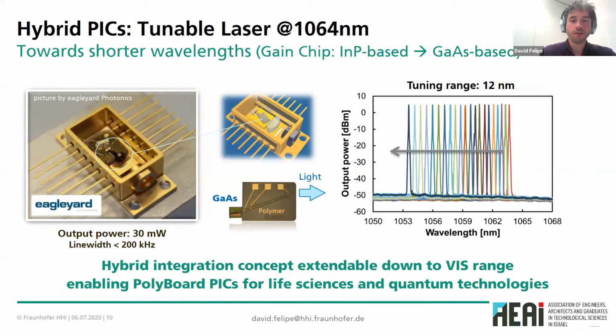So the tunable laser concept can be extended also to other wavelengths. I mentioned before that polymers are transparent in a very broad range of wavelengths. So the typical C and O band wavelengths for telecommunications, but also for spectroscopy applications, it's interesting to go to shorter wavelengths, so 785 and 1064 nanometers, for example. And this is a tunable laser based on the same principle that shows that just by changing the active section from indium phosphide to gallium arsenide, and of course by redesigning the Bragg gratings to be able to design at that wavelength, one can achieve also a tunable laser operating at these wavelengths.